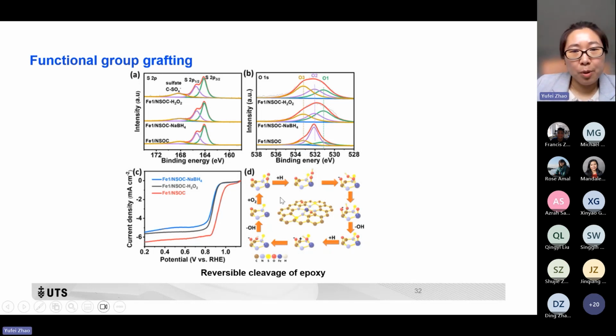So we have proposed the mechanism: except for modulating the electronic structure of the iron in this atomic structure, this epoxy group may also participate in the reactions. It can form a reversible cleavage of this epoxy to form oxygen and carbon with negative or positive charge, and facilitate this rate determining step, and then facilitate the ORR process.